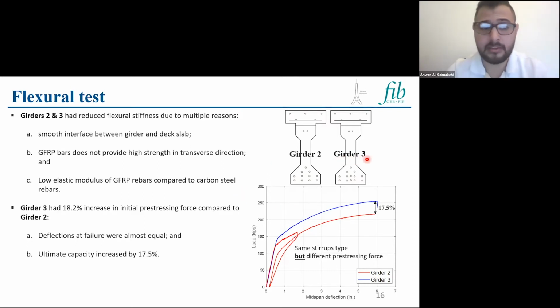Girder 3 had an 18.2% increase in the initial pre-stressing force because of the 2 additional strands, and this did not influence the deflection, but it did influence the ultimate capacity. As we can see here, it increased by 17.5%.